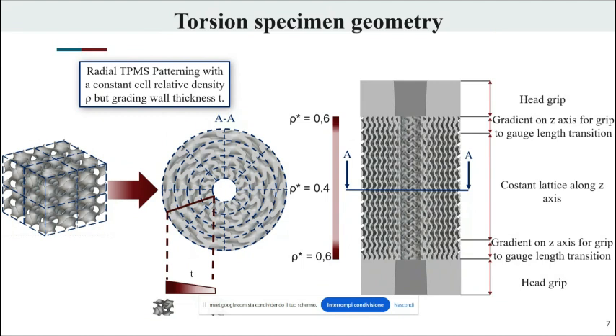And the second one can be seen in the section in the right part of the slide. We changed the wall thickness from the gauge length toward the head grips, so from a relative density of 0.4 toward a relative density of 0.6 in order to avoid the fracture in the interface of lattice and head grip.